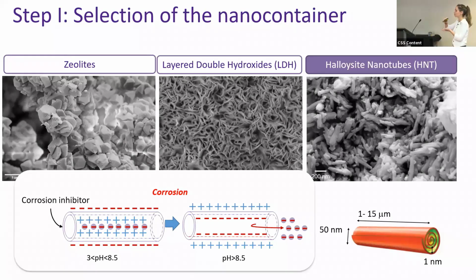When pH increases, just like it happens when magnesium corrodes, there is a change in the charge distribution of the nanotube. So the outside becomes positively charged and the inner lumen becomes negatively charged. And this will force the release of the inhibitors because they will repel each other.